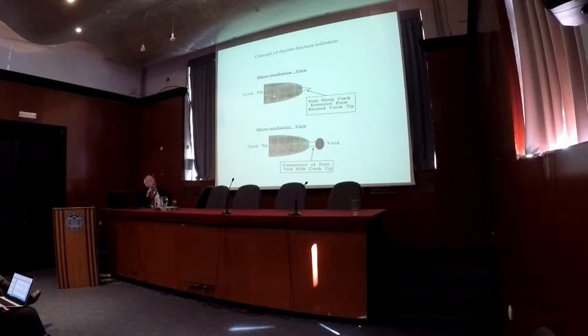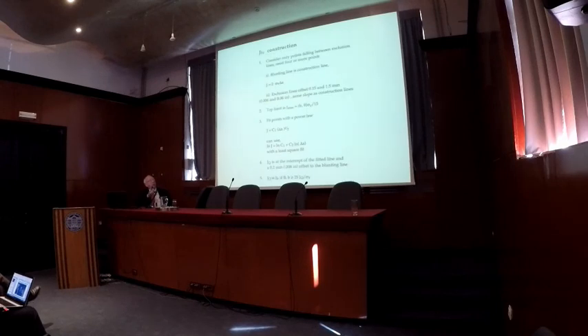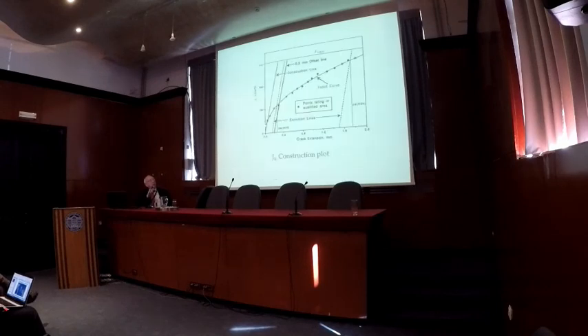Now, here is an idea of where to get a single point. When the sharp crack develops in front of the blunted crack, call that point J1C. And micromechanically, that could be when the first void coalesces with the crack tip, but that point's very hard to find because you can't look into the specimen and see that point, so you do a construction method. And here's the construction method.